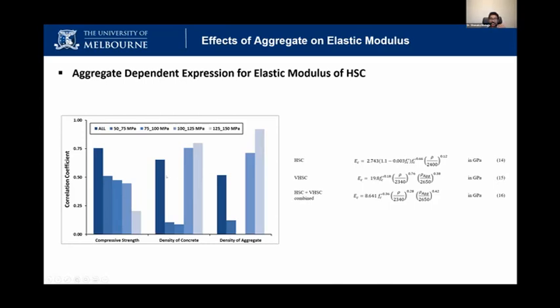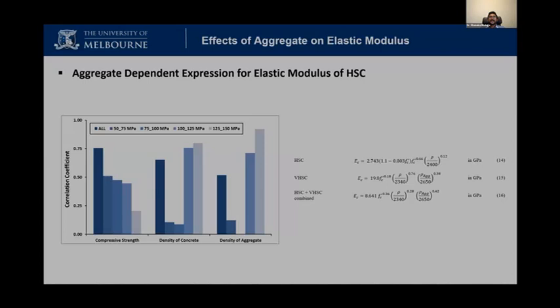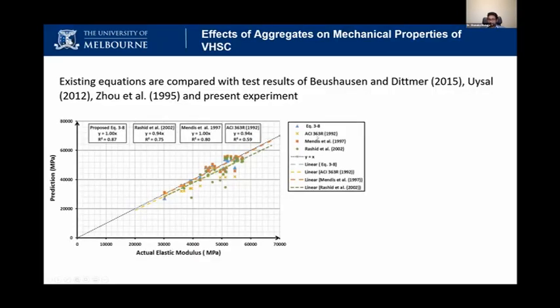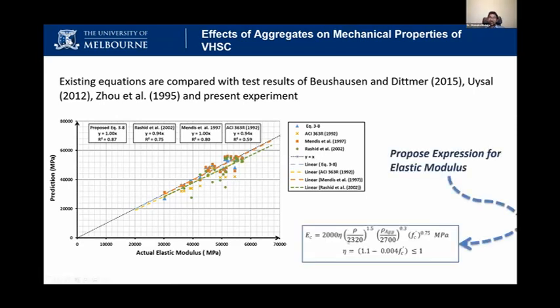We know the elastic modulus is defined using the strength and the density of concrete in our codes. But what we found is that for ultra high strength concrete, we have to think about including the aggregate properties, the aggregate density, in order to find the elastic modulus. Actually, we developed an equation and we published these new equations. We compared them with the different codes, and we came up with a new design equation to calculate the elastic modulus.